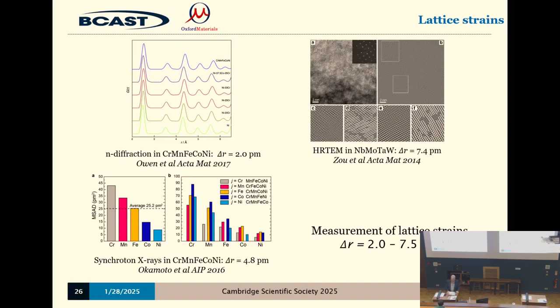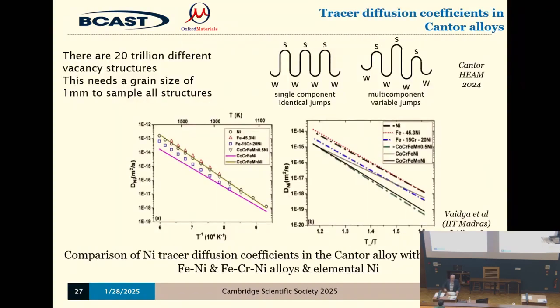the interesting properties. So to go through them very quickly, there's 20 trillion different structures around what's called a vacancy. The way atoms move around in solids, crystals, is by jumping into vacancies. There's a vacant site, occasionally an atom missing. And the structures vary enormously for the same reason, around the vacancy. So if you have a single component material, every time an atom jumps, it's got the same profile in energy. It jumps from its starting position to a new position and goes over a saddle point. So all the jumps it does are the same.